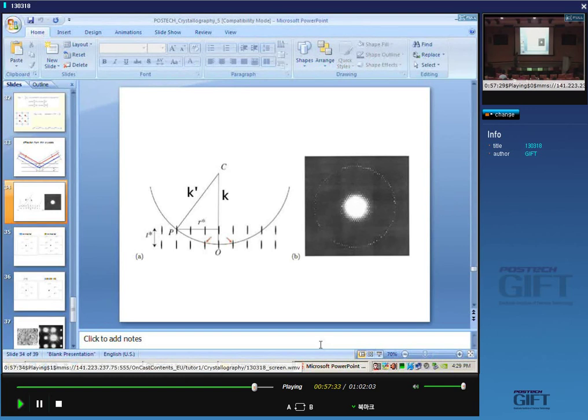And remember also that the reciprocal lattice is a three-dimensional lattice, and the Ewald sphere construction that we considered before was just looking at one layer of the reciprocal lattice. But you can set up conditions in the transmission electron microscope where the curvature of the Ewald sphere is such that you will also intersect another layer. And then you get this ring corresponding to diffraction from the second layer. Now this is very good because that gives you three-dimensional information on diffraction, not just one layer.